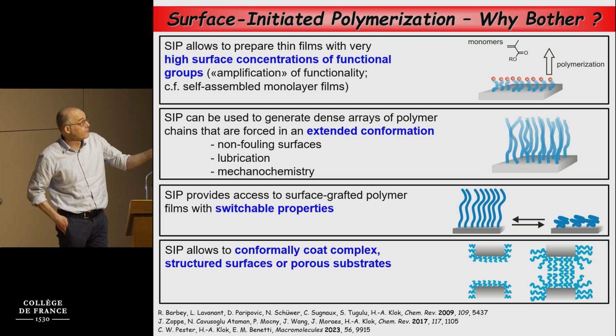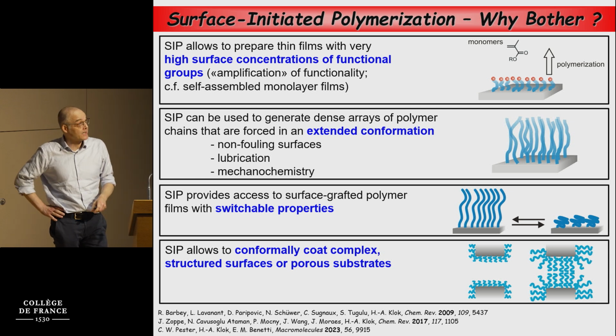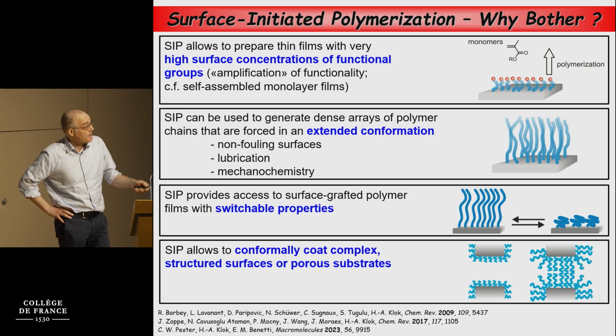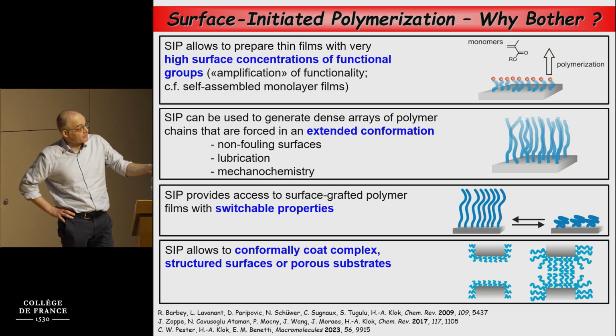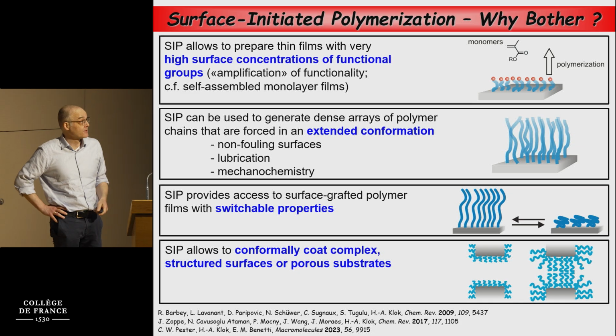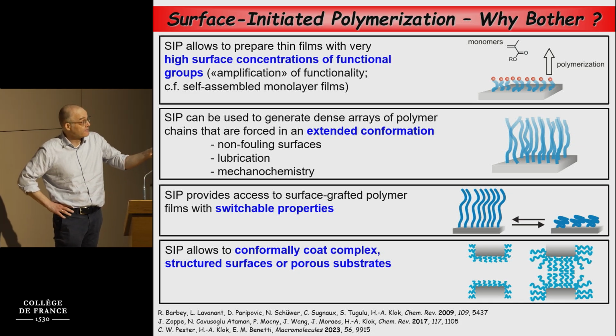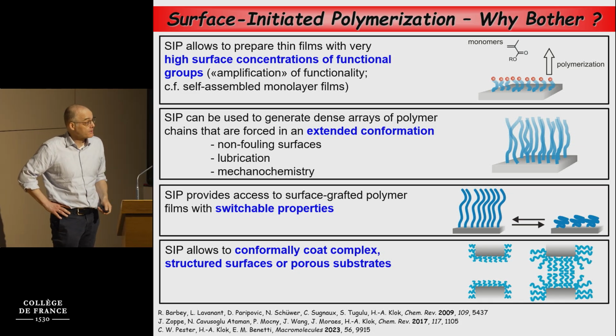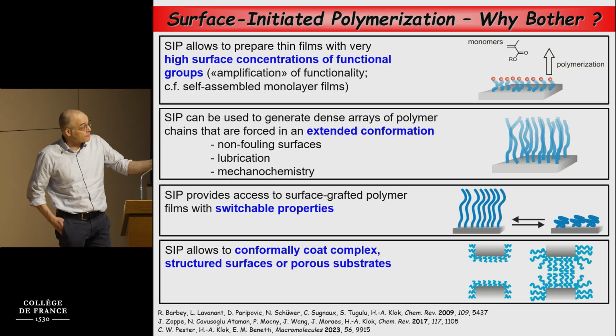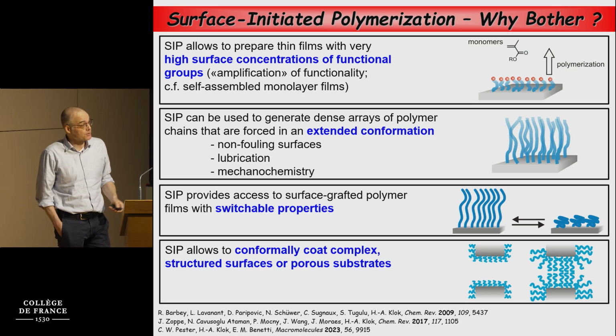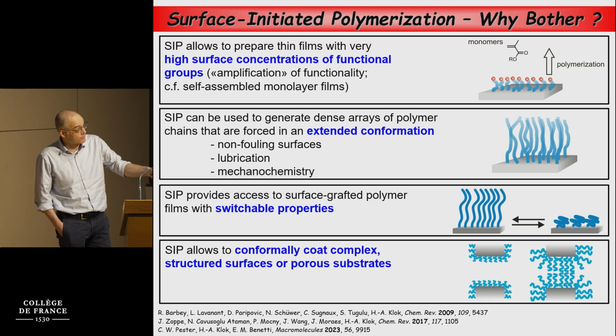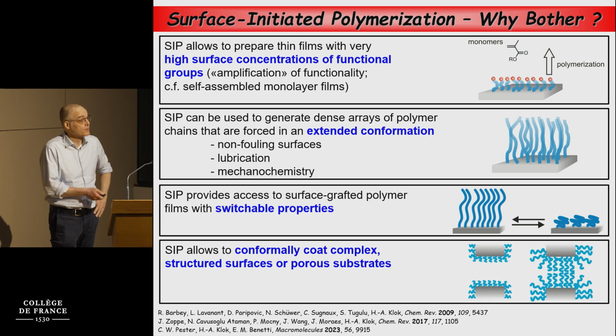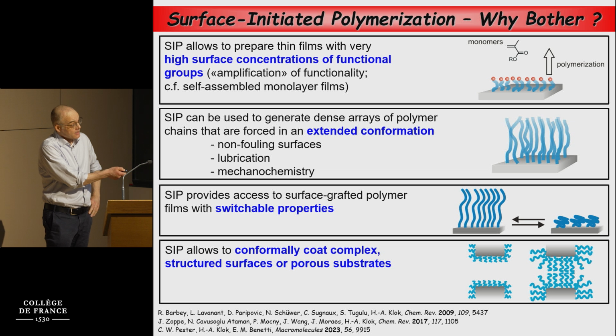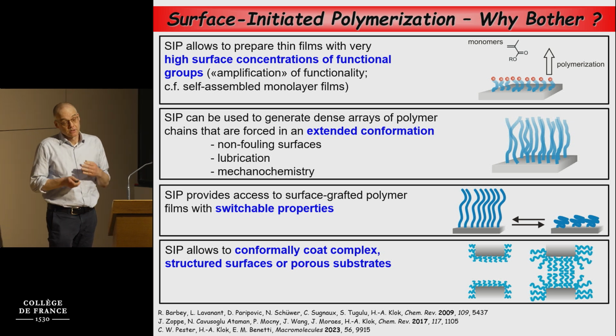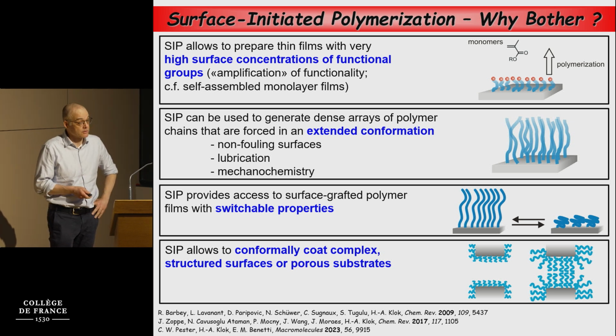It allows us to prepare thin films that present a very high concentration of functional groups. This is interesting for diagnostics and all sorts of biosensing events. The stretched chain conformation of polymer brushes is also very unique, and it underlies properties such as unique non-fouling ability of these surfaces, and lubrication properties. If you introduce appropriate functional groups, you can actually make surfaces that basically switch properties, because properties are often related to conformation. And since this is a wet chemical approach, it's also a very powerful methodology to modify conformal, complex, or structured or porous substrates.